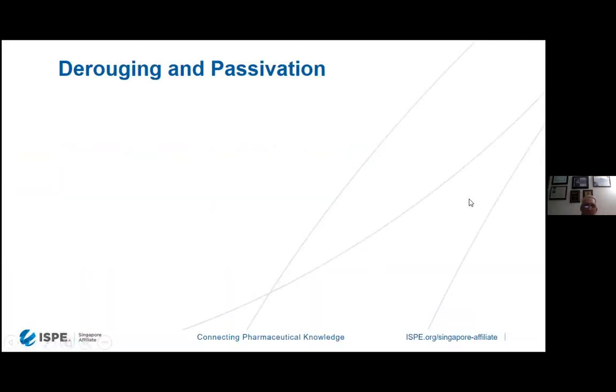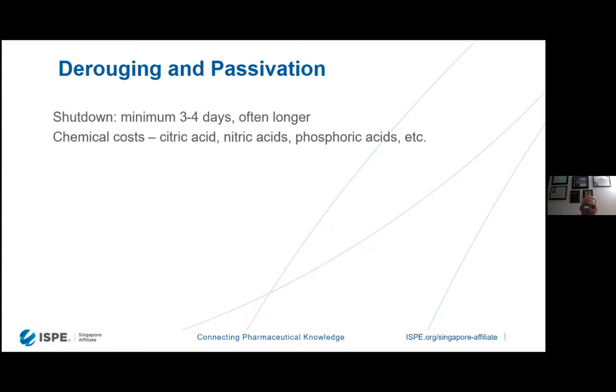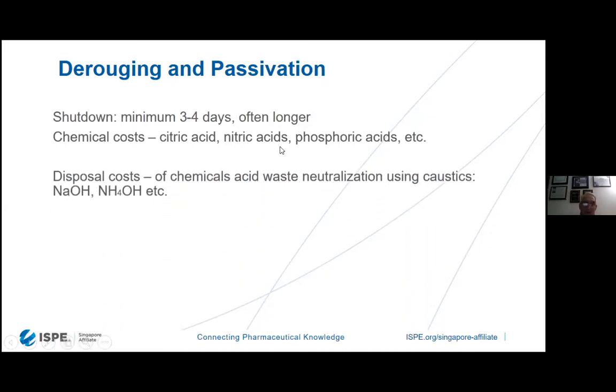Some of the applications that we look at: when we do a derouging passivation, how long does it last? Well, the minimum is usually 3 to 4 days. Sometimes it's longer, depending on how many loops there are, how large the water system is, what the administration is, etc. There are chemical costs associated, which may be citric acid, nitric acid, phosphoric, etc. Most of the time in Asia, I think they're using citric acid. Sometimes phosphoric acid is also used. It costs money. But in order to get rid of those chemicals that are in the water, we have to do what is called acid waste neutralization. That's using caustics against the acid in order to bring the pH to as close to 7 as possible.